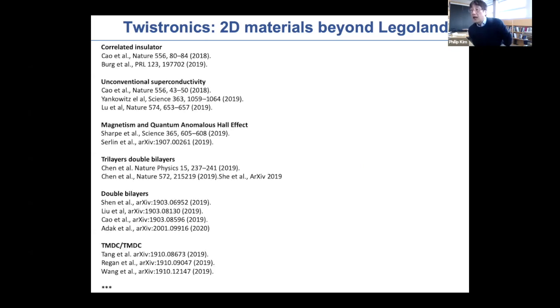I just collected some of these experimental papers that I could quickly search through. Of course, in twisted bilayer alone, the magic angle twisted bilayer, there is not only a correlated insulator, but also a superconductor. Alan mentioned that there are magnetisms, and the quantum anomalous Hall effect has been seen in those kinds of systems. And then people quickly searched beyond this twisted bilayer, for example, the trilayer system, where the flat band appears, either aligned with the boron nitride or not aligned. This trilayer system also shows correlated insulating behavior, superconducting behavior, as well as some quantum anomalous Hall type behavior.